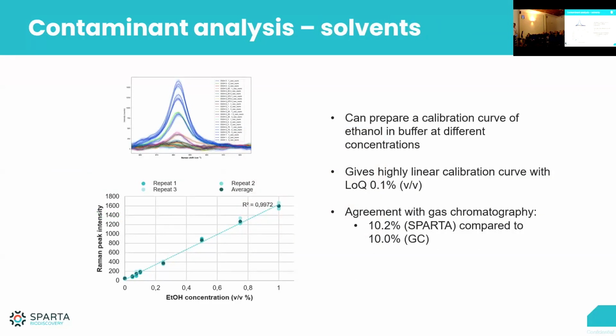And we can also compare this, for instance, to GC. We did this for ethanol. LNPs are usually made in an ethanol phase or other kinds of solvents. Raman is actually very sensitive in detecting organic solvents in the solution. We can make a calibration curve here, and we compared that against GC on how accurate it was. This is, again, a very easy test. When you do all these normal SPARTA measurements, you get this basically for free. We can just look at a specific position. Is there ethanol left in your LNPs or not? And it's very sensitive to detect that.